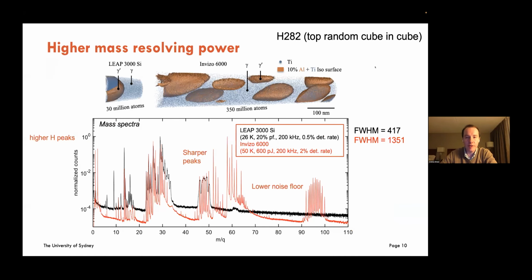And just some notes on the mass resolving power. Again, I haven't done a big longitudinal study here yet, but just comparing the mass spectrum between these two data sets, we can see that we get significantly higher mass resolving power, really high full width half maximum measured off the main nickel peak here.